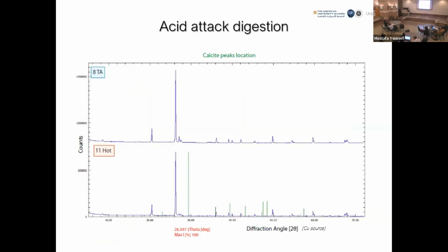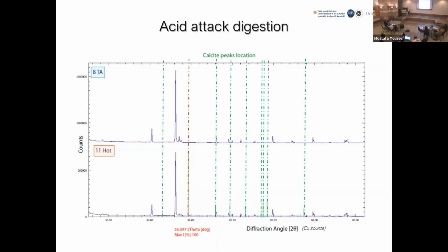To do that, I used XRD again. And as you can see here, the results from the test at environmental temperature and the hot temperature are more or less the same. I would like to focus your attention on this green line, because it represents the position of the calcite peaks, where calcite should be located if my sample still had calcite. And as you can see, they are not present anymore. Moreover, the red line represents the main characteristic peak of calcite, and as you can see, it is not present. This means that the acid concentration and the procedure that I used were correct.